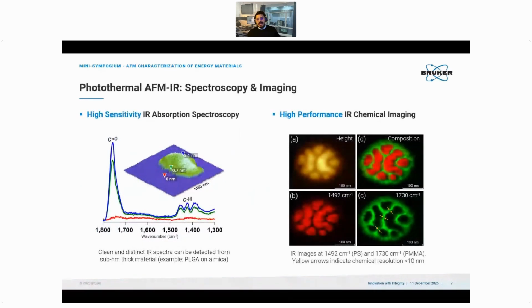Now, this allows us to do two things. The first part is spectroscopy, right? So similar to what you would do with any infrared study, you would want to see the absorption spectra on the surface of your sample. In that case, we will position the tip on different areas of the sample. So obviously we are using AFM, so we can image the surface. We can do that either in contact mode or tapping mode or force curve based modes. I'm not going into these details now, but basically you get an image of the surface, even in peak force. And then you position the probe, you choose positions of interest on that surface.